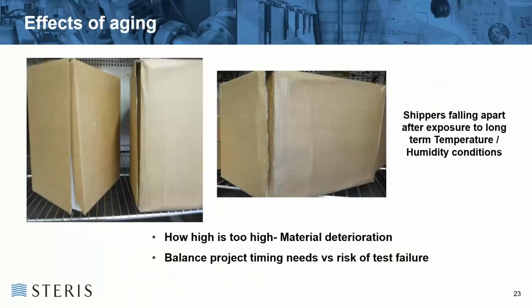If you look at, say, the two pictures here in relation to shipper boxes, the shippers started to fall apart in the aging chamber after a relatively short period of time. For two reasons: the temperature was very high and the relative humidity within the chamber was very, very high. And that destroyed the adhesive in the manufacturer's joint, and the box started to fall apart. If this was a real-time scenario where your product was being shipped out in the field and exposed to very high humidity, this could also happen.